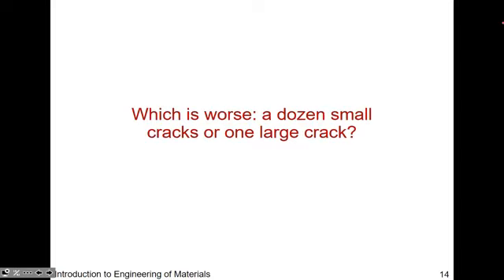So if you're thinking about what is worse in life, having some small cracks or one large one, it really depends on the history of the material and the future of the material. If you have some small cracks, that might not be so bad, even if you have a lot of them, because these cracks are tiny. I'm comparing two regimes where if you have one large crack that's above some critical crack length, that would be a very bad thing. You would not want that. You might prefer a bunch of tiny cracks that are static, and at least in compressive strain, nothing will happen, right?